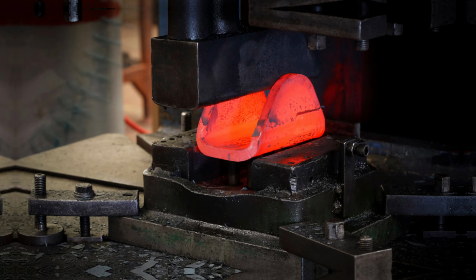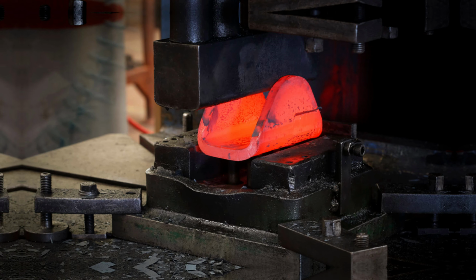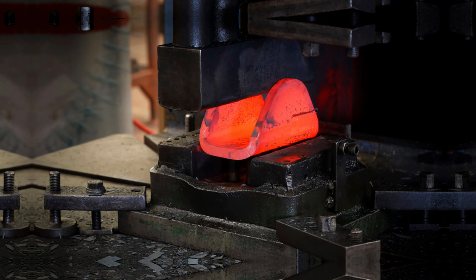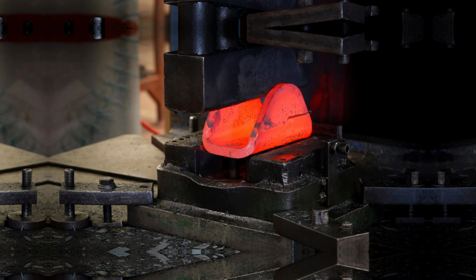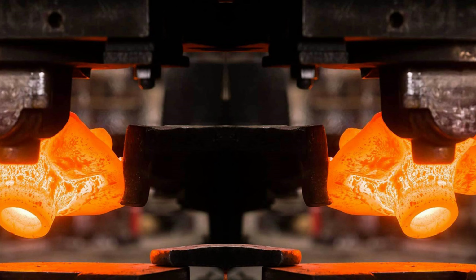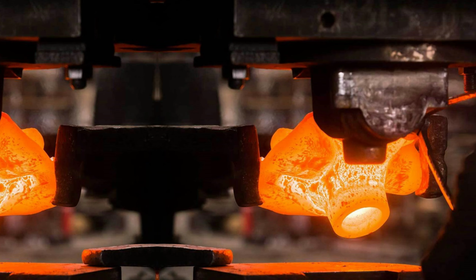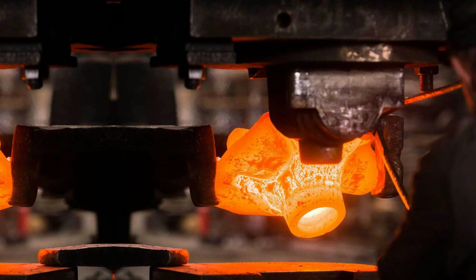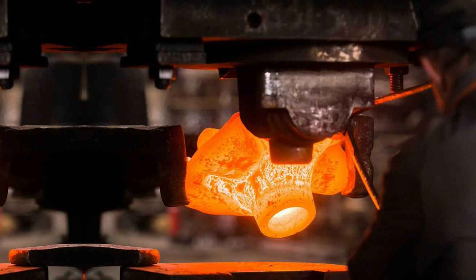Steam hammer forging showed yield strengths 8% higher and ultimate tensile strengths 12% higher than servo press work. More significantly, elongation to failure measured 24% greater in the steam hammer samples. The metal could stretch further before breaking.